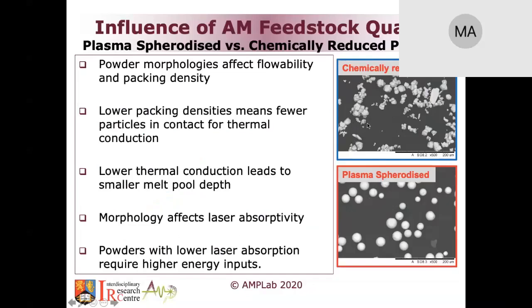You can see that the powder morphology, of course, will affect the flowability, as I explained. It will affect the packing density of the powder in the chamber. Lower packing actually means that fewer particles are in contact, so it affects the thermal conductivity in the chamber. Lower thermal conductivity also will reduce the melt pool depth, so it will reduce the level of remelting, which is ideal in additive manufacturing to ensure that the microstructure is homogeneous and that the layers are essentially attached to one another. The morphology even affects the laser absorption.